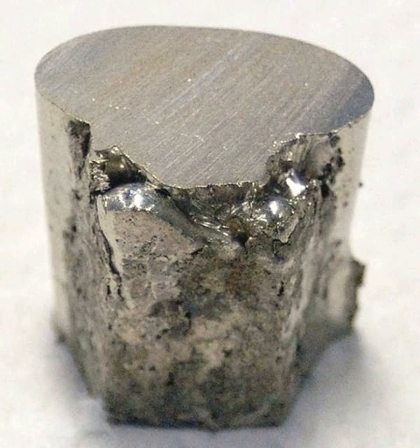Mond process. The purest metal is obtained from nickel oxide by the Mond process, which achieves a purity of greater than 99.99%. The process was patented by Ludwig Mond and has been in industrial use since before the beginning of the 20th century. In this process, nickel is reacted with carbon monoxide in the presence of a sulfur catalyst at around 40 to 80 degrees Celsius to form nickel carbonyl. Iron gives iron pentacarbonyl, too, but this reaction is slow. If necessary, the nickel may be separated by distillation. Dicobalt octacarbonyl is also formed in nickel distillation as a byproduct, but it decomposes to tetracobalt dodecacarbonyl at the reaction temperature to give a non-volatile solid.